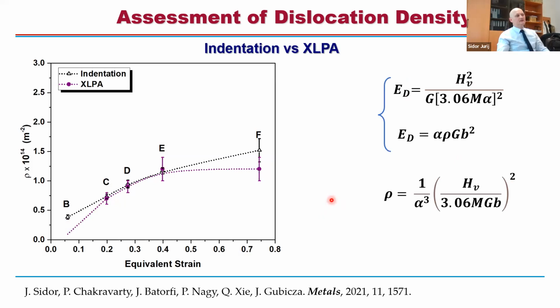Then we compare the results, what we got from the indentation technique and X-ray line profile analysis. And in fact, we were quite amazed that the trend was very, very similar. And also the order of magnitude was identical. There will always be some differences between techniques, which is evident, right? So we published this work recently about the evolution of dislocations in the 1050 aluminum alloy subjected to different straining